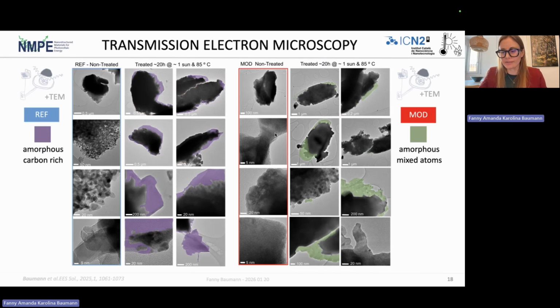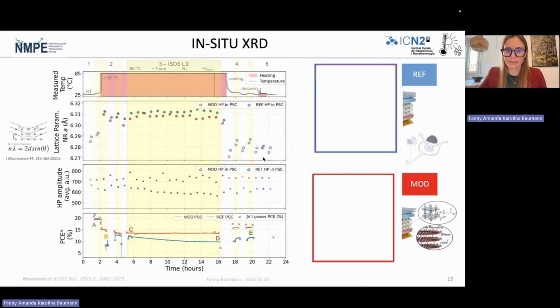However, we did see that there was a loss of perovskite material, and we asked ourselves, well, where is this loss going? Because if you look back here, you can see that there's even also a recovery at the end, together with the recovery of the performance. So the material should still be inside the device. So we wanted to see what happens here.